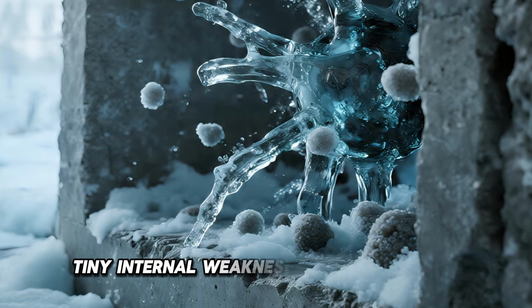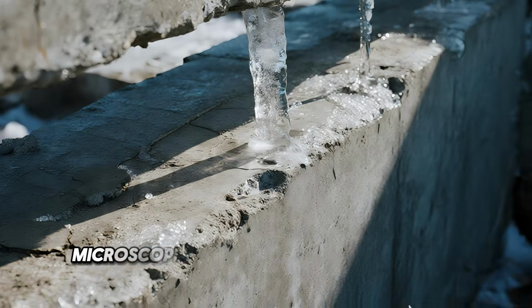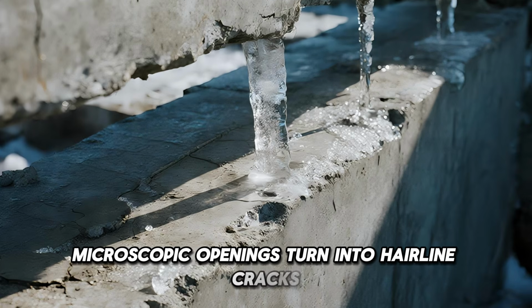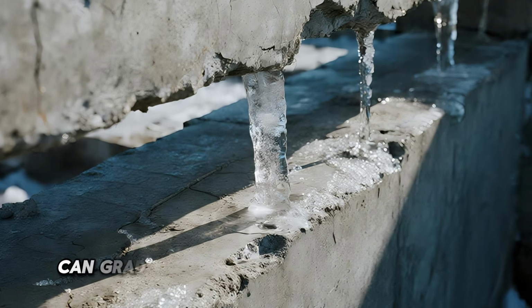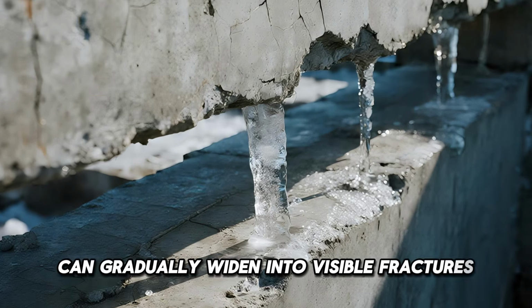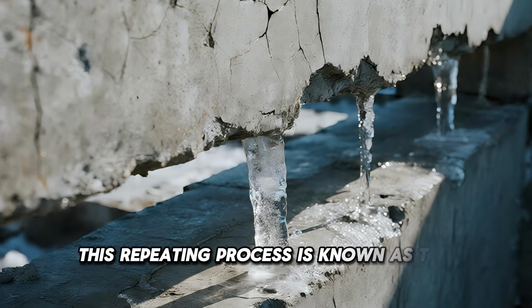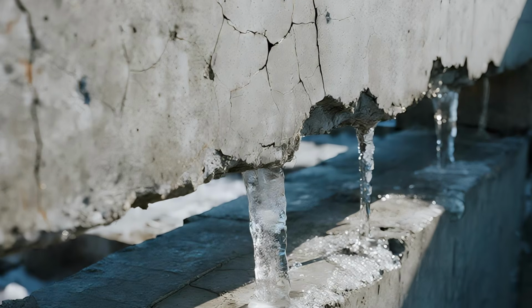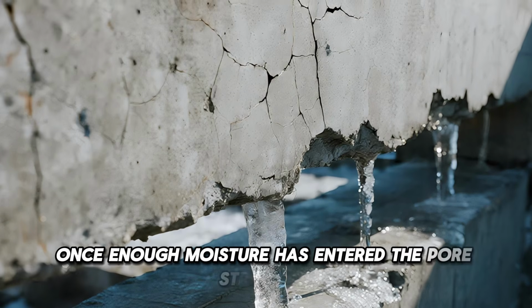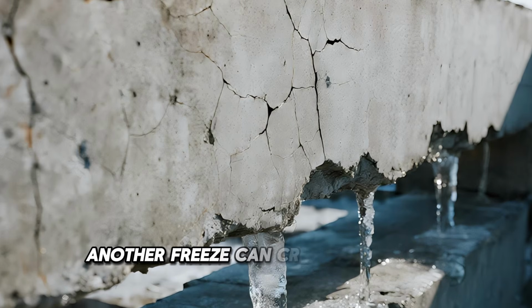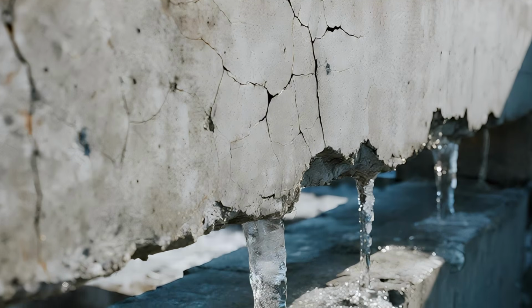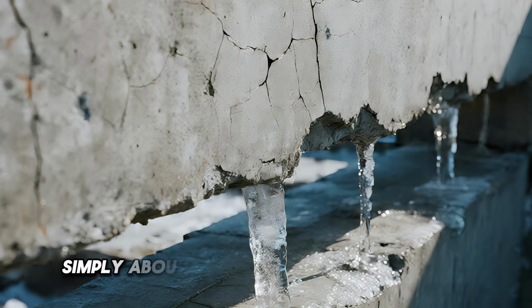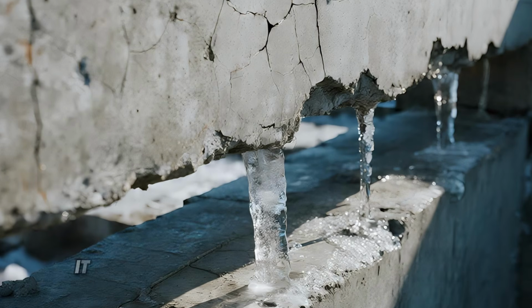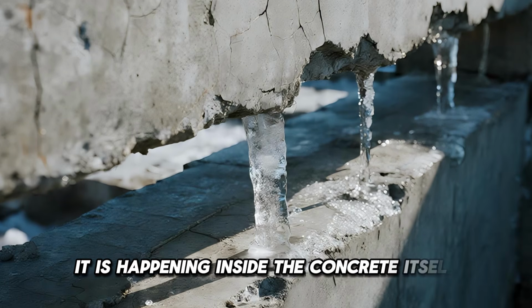Tiny internal weaknesses become larger. Microscopic openings turn into hairline cracks. Hairline cracks can gradually widen into visible fractures. This repeating process is known as the freeze-thaw cycle. Once enough moisture has entered the pore structure, another freeze can create enormous internal stress. The damage is no longer simply about what you see on the surface. It is happening inside the concrete itself.